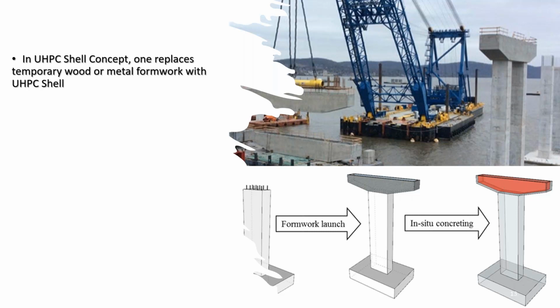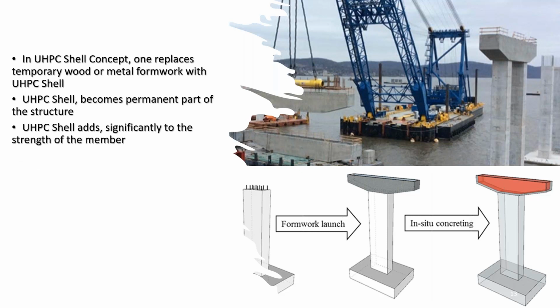So the UHPC shell in this concept replaces the so-called temporary wood or metal formworks and facilitates the construction. What's important is that the UHPC shell becomes a permanent part of the structure. You don't remove it; it bonds with the concrete that you put inside and becomes an integral part of the finished product. Even that small thickness of the UHPC shell adds significantly to the strength of the member.